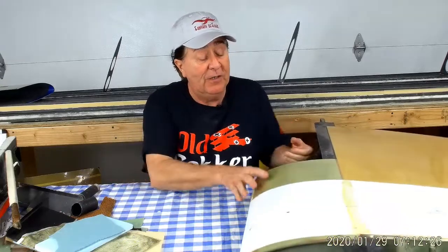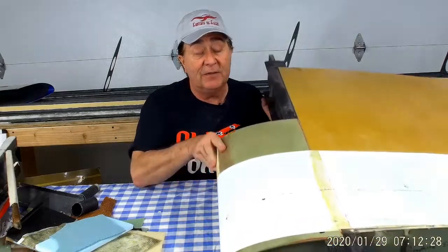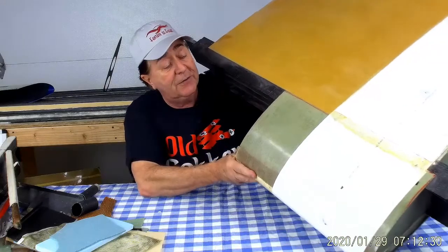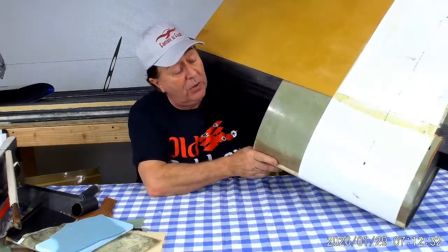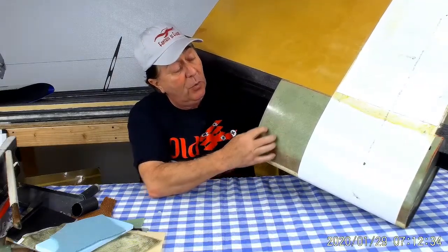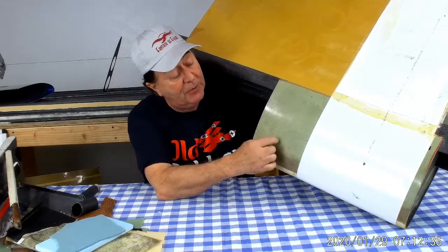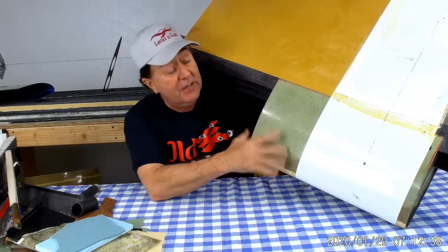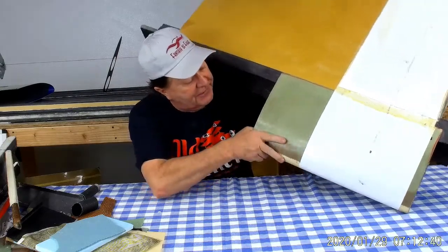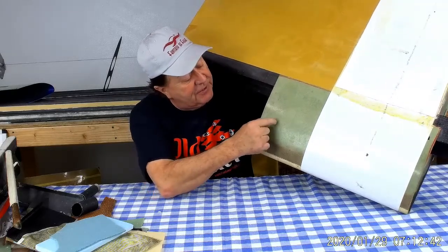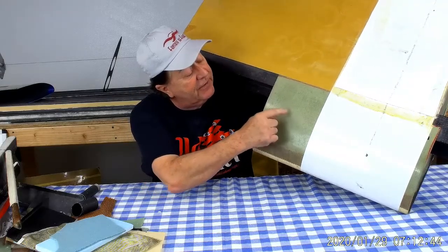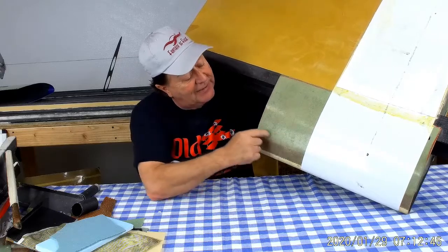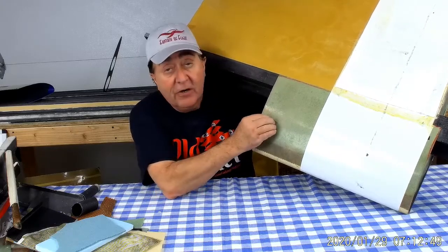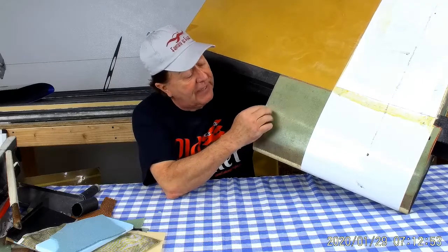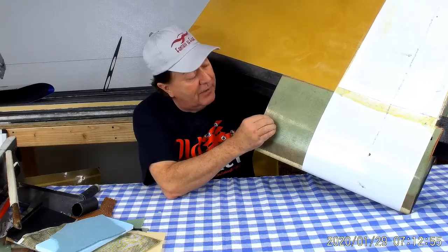Now, while we're here, I wanted to show you a little example. I talked about the wet transfer layups, and you'll see it's readily apparent here when you don't have the fabric wet enough when you transfer it. I hope you can see it on the surface here. I'll move this around a little bit. You see some dark areas here, and then you see some lighter areas, and it looks like dots and so forth. The dark areas is where there was enough resin to bond it securely to the foam, and the lighter areas is where it was not bonded well to the foam.